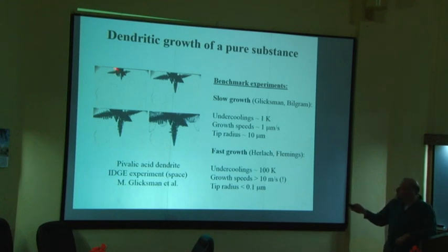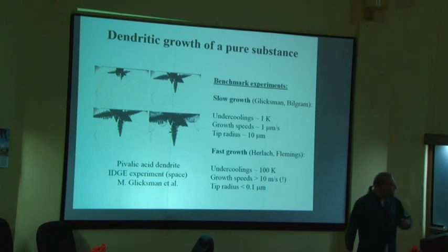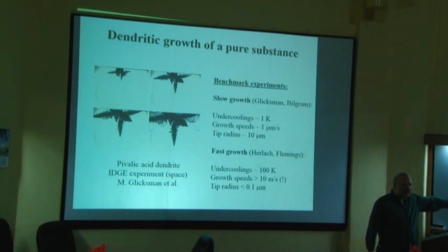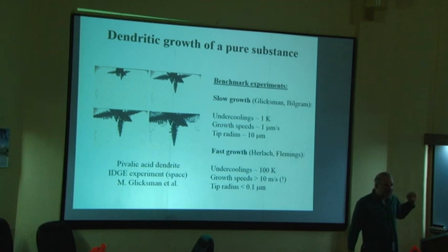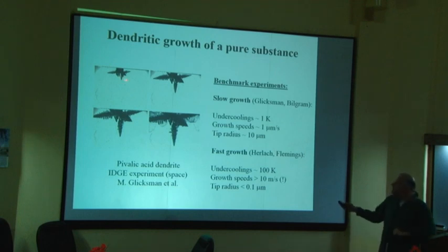So what happens, the crystal grows, and it brings its interface up to very close to the melting point. As Abik has mentioned, the Gibbs-Thomson equation tells us that up to some curvature effect, the temperature should be equal to the melting temperature. So close to the crystal, we are at the melting temperature. Far from the crystal, we are undercooled. So there is a temperature gradient that goes from the crystal away to the liquid, which generates a heat flux from the crystal to the free space. And this allows the crystal to continue to grow.